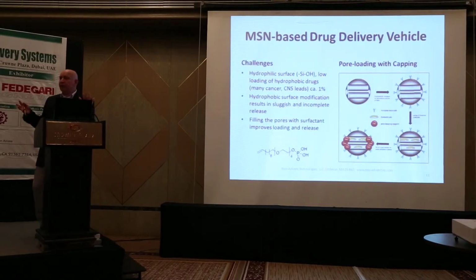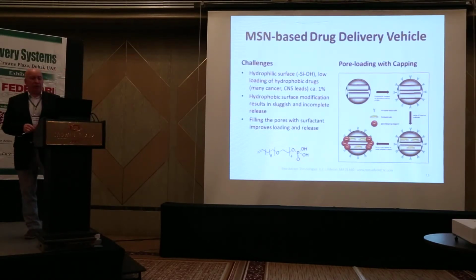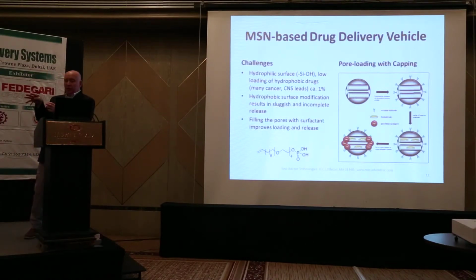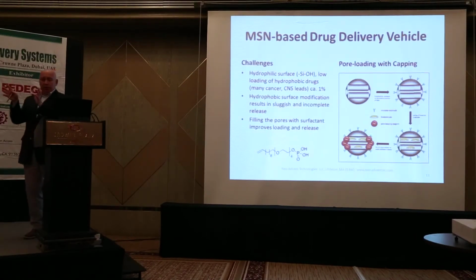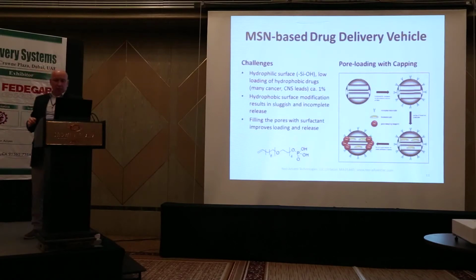So what options do we have? What people try to conceptually show? I think the possibilities are really exciting because you can load the drug inside of the pores. You can decorate the surface of the particle with whatever targeting moiety, and then you can potentially clog the pores with temporary corks and then open them up. Okay? So what are the problems? Unfortunately, the silica surface is relatively hydrophilic. You have a lot of OH groups. So when you try to load drugs, and a lot of them are hydrophobic, it's very difficult. So the load levels are relatively low.